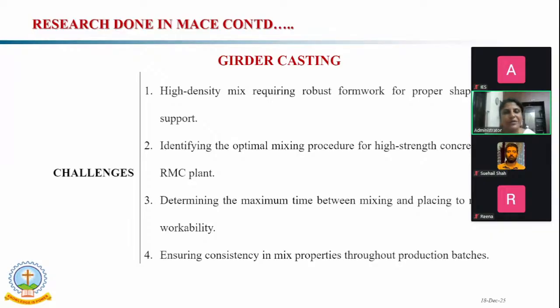Then the optimum mixing procedure. Till that point we had considered only the laboratory procedure. In the laboratory procedure, we initially put the aggregate and the binders and mix for 2 to 3 minutes to get proper dispersion of the silica fume. Then, in order to control the initial heat of hydration due to the very low water to binder ratio, we considered ice cubes. We initially added 80% of the water as ice cubes to the well-mixed binders and fine aggregate, and continued mixing for 5 to 6 minutes.